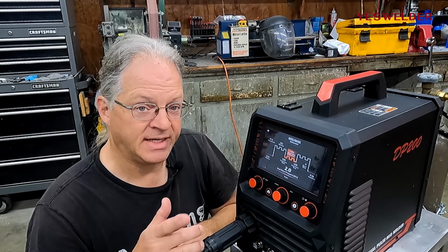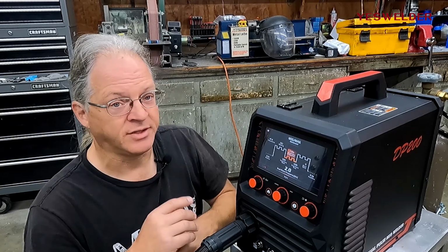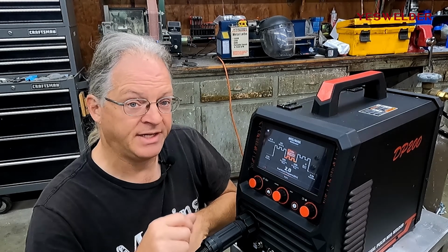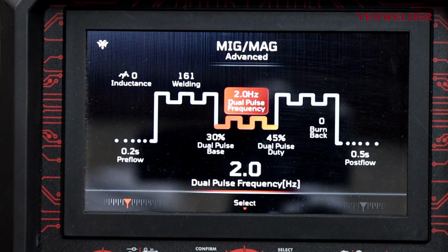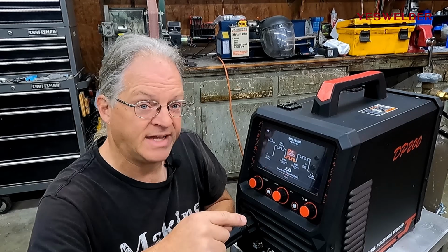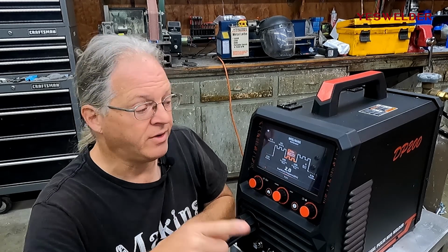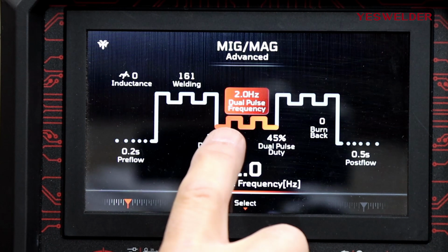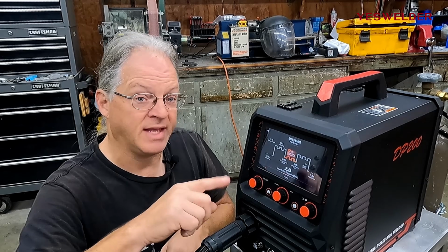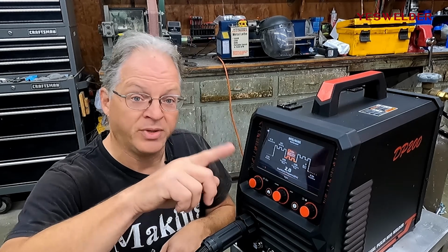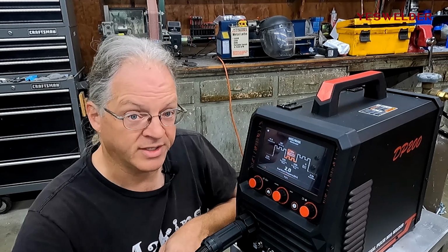Okay, so let me explain the settings that I just used on that 16 gauge aluminum. One of the first things I had to change was the frequency. That's because I am moving the torch faster on this thinner material. So I bumped the frequency up to 2 Hertz. That means that double pulse loop makes 2 complete loops twice per second.